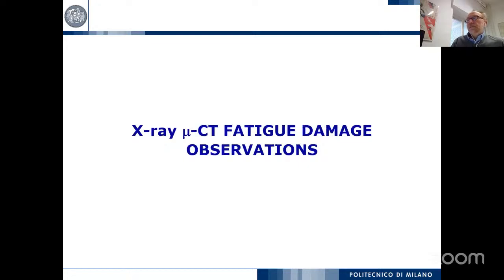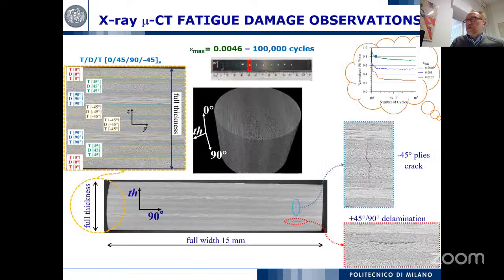And then why did this happen, in terms of the damage mode that we observed inside the material with micro-CT? This is an observation of one sample cyclically loaded at this strain level after 100,000 cycles, meaning that we are working at this level in terms of reduction of stiffness and strain level. So you see that what we have is fragmentation, or intra-ply cracks, that mainly happen in the 45 ply. And then this will gradually and slowly move to the interface. This is what we expect in terms of evolution and sequence of damage modes.